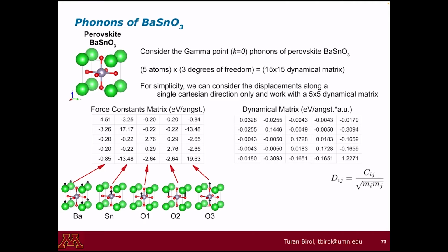Okay, sorry, yeah, I understand, but what I'm asking is, generally, how large can I make these displacements of the atoms? So in this compound, I don't recall exactly what I used. I must have used something like 0.1 Angstroms. Sorry, 0.01. Yeah. Now, if you are in doubt, and especially in metals, this can be an issue.